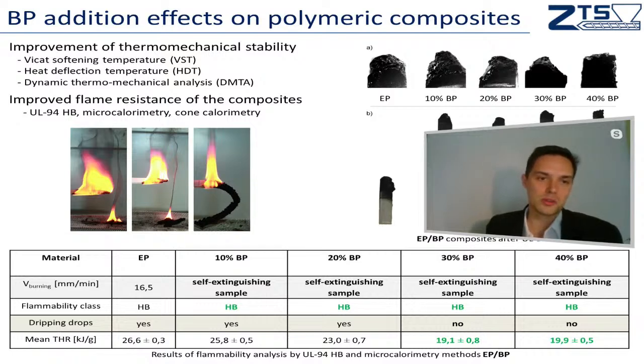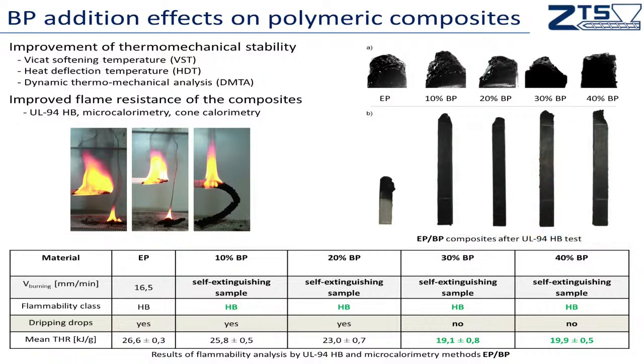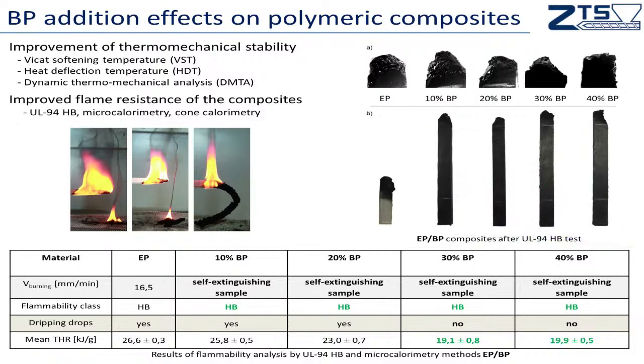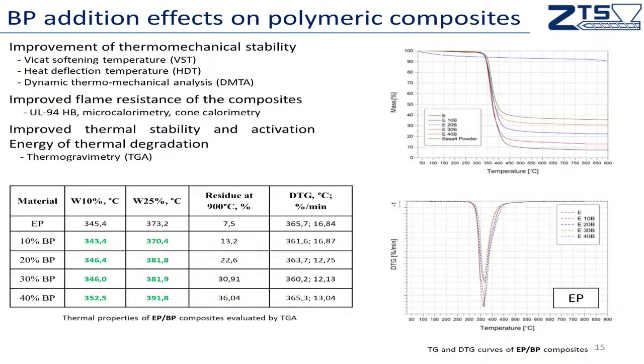At the bottom of the table we can also see that the mean total heat release evaluated by microcalorimetry was also reduced. So maybe the addition of the basalt powder did not create totally non-flammable materials, but in the case of hybridization and using different commercially used intumescent flame retardants, we can obtain low-cost and safe materials for different branches of the industry. And if we move to the next slide, we can see that the thermal degradation was also decreased. So if we talk about flammability, we always think also about the thermal stability of the material.